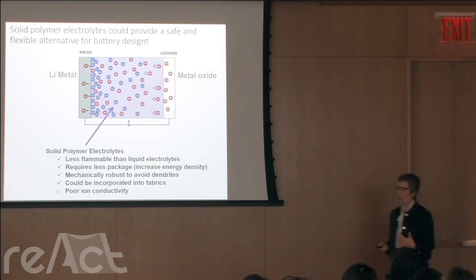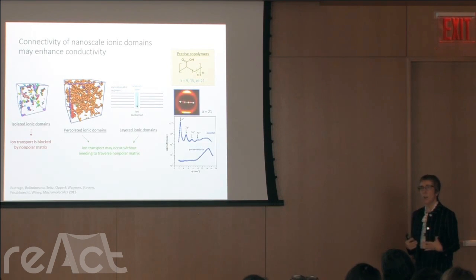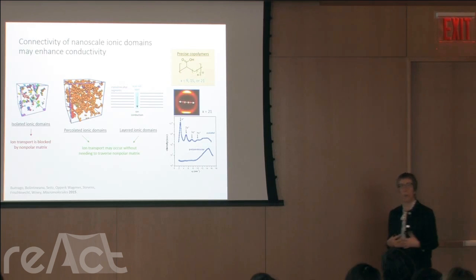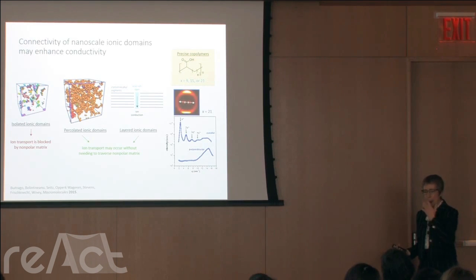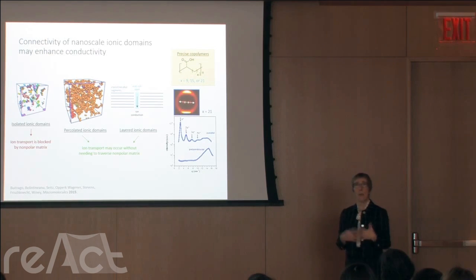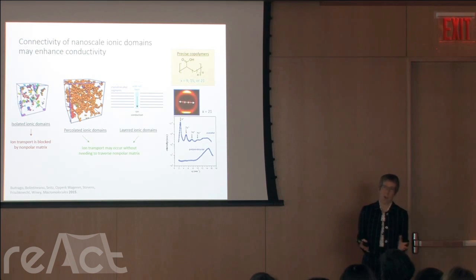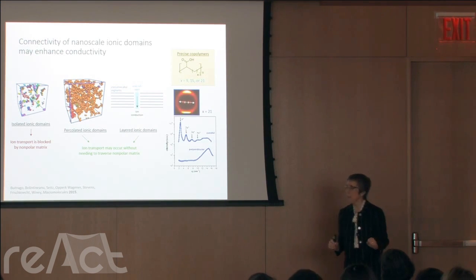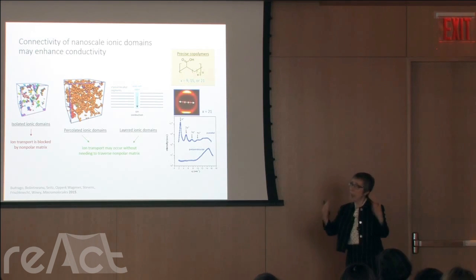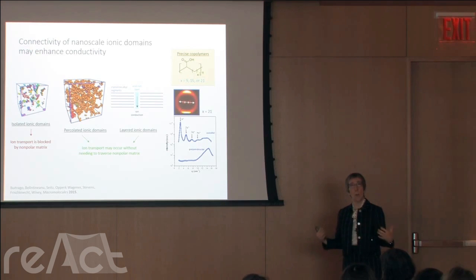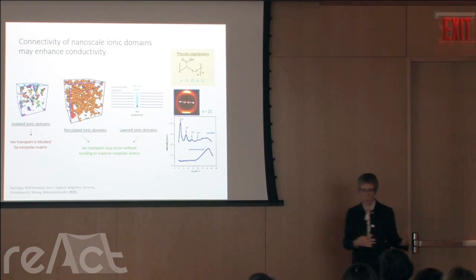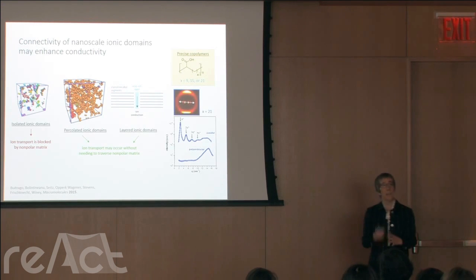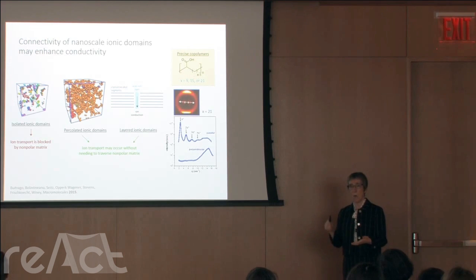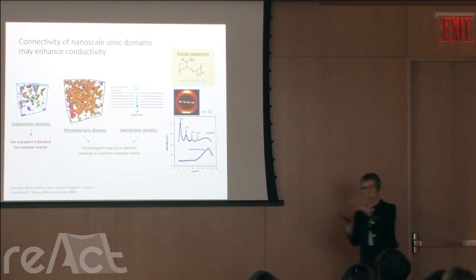So in our work, we've been looking at single ion conductors, one type of solid polymer electrolyte. And we've come upon two types of ionomer structures that could be viable for faster ion transport. Now, the chemistries in which we've found these interesting structures are not really viable as single ion conductors. They're based on carboxylic acid. But the concept of these morphology types, I think, is viable. And so what we're hoping to do within ACT3 with various partners, both from Giant and from Solvay, is to design chemistries that are likely to form these morphologies. So we have a morphology in mind, and now it's a matter of designing the molecules that will produce these morphologies.